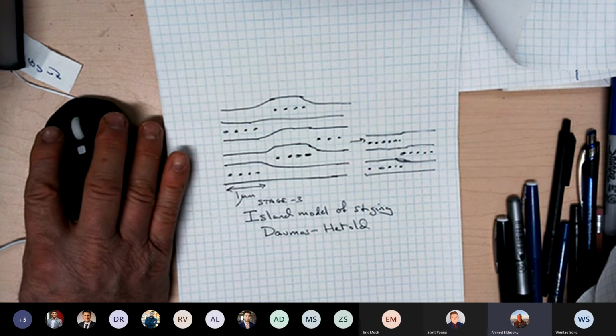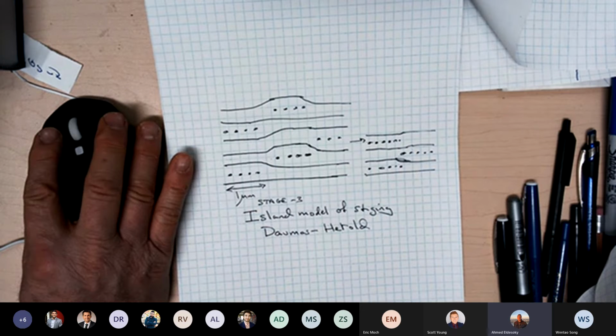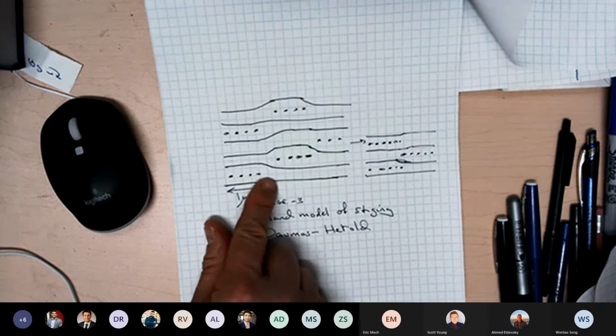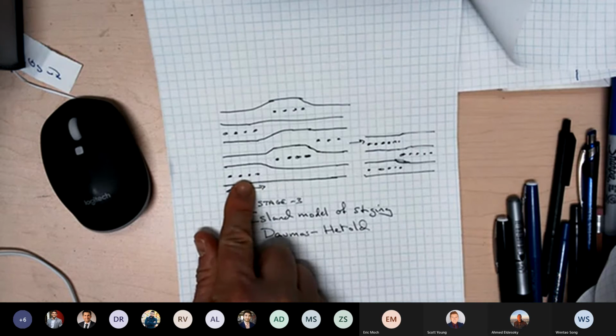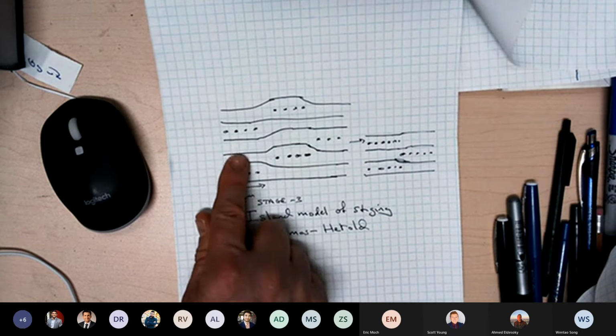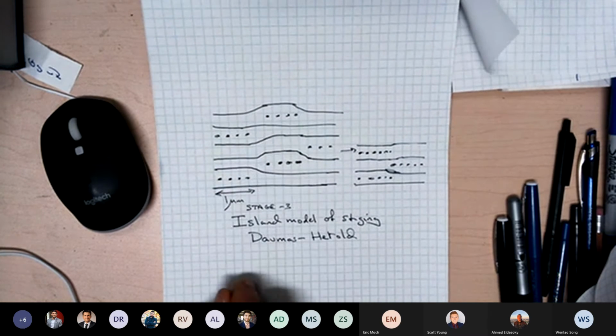So all this model is saying basically is that you form islands of lithiated graphite that get bigger and bigger as you add more lithium, and that's how you get the different stages. That's basically all this is saying, right? That's basically what it's saying, and it's saying that lithium atoms within the layer attract one another, and from layer to layer they repel one another, so that you tend to form these islands that don't want to sit on top of each other.